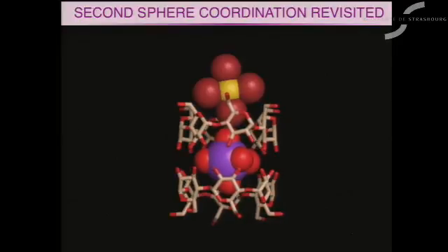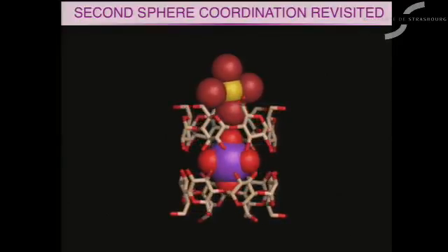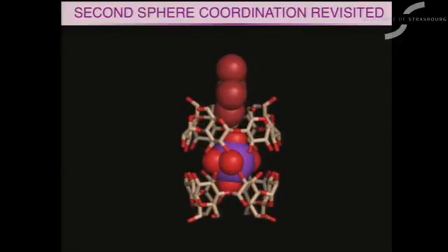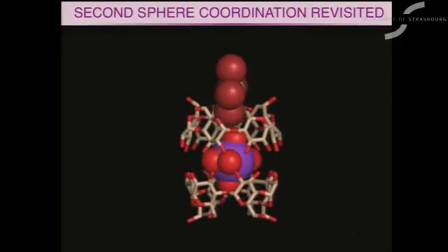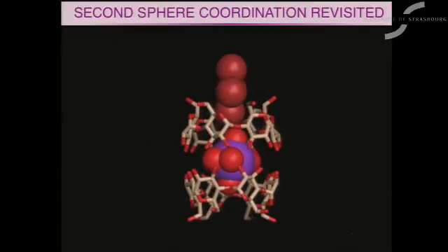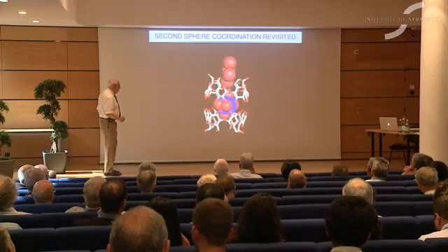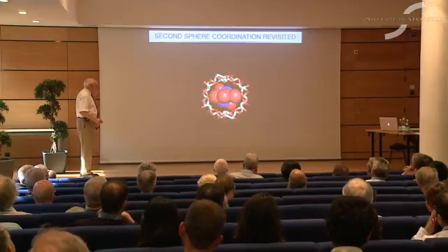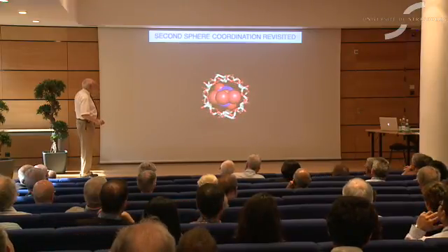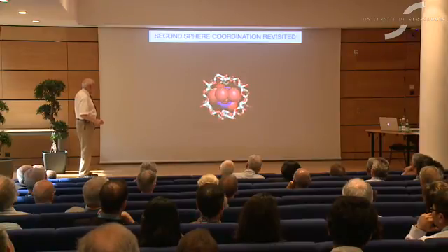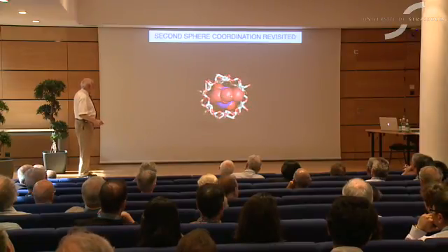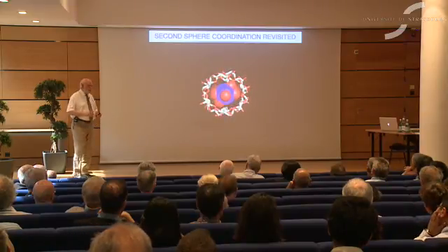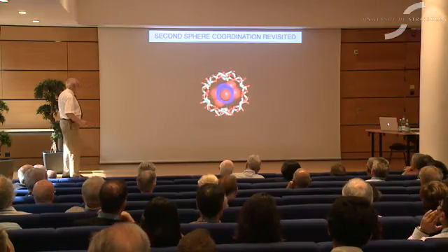So what? Probably against the clock. This shows very well what I want to talk about. It's a 2-to-1 complex. We have two rings around what turns out to be a potassium with 6 waters, so it's octa-coordinated. And here's our tetrabromoaurate. And notice how the methylenes of the primary hydroxyl groups are pointing into the bromines here, so C-H···Br interactions.